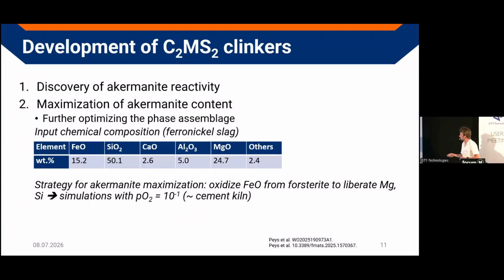We started here from the same slag. And what was our strategy now? We want to oxidize the iron oxide. You see there's still quite some iron oxide. So to take it away from the forsterite, and then we have some additional magnesium, we have some additional silicon. If we then also put additional calcium, we can further maximize this akermanite.